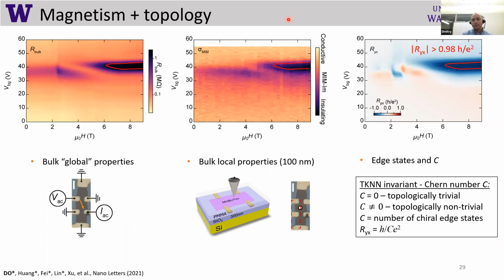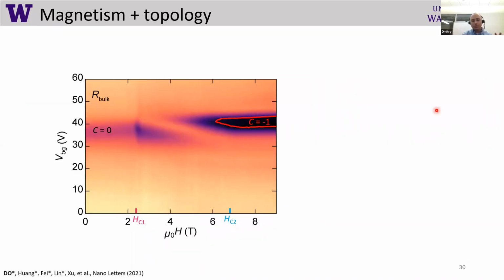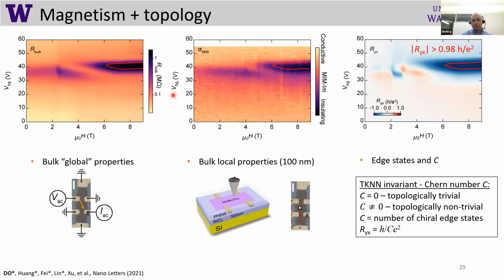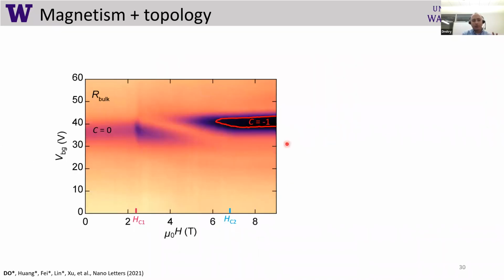So now I overlap all these 3 maps with a contour. This contour essentially locates, inside, the Rxy which is higher than 98% of h over e squared. So this is an arbitrary number, but inside this, we have Chern number -1. And outside of that, we have Chern number 0. So now let's focus only on one map. Here I had 3 maps, but essentially they inform us on more or less the same thing. But now let's focus on one map of bulk conductivity and check what's going on here.